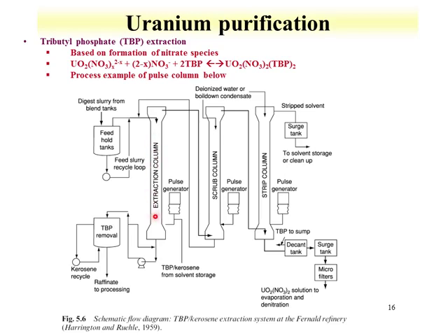As that drop moves down the column, it will form the uranyl nitrate tributyl phosphate species, which then gets extracted into the column. The aqueous phase going here, the organic phase containing the uranium here. The organic phase is taken, added to the scrub column. So this could be the same concentration of acid, so let's say 3.5 molar. As the organic bubbles float up, any metal ions that aren't the uranium can be preferentially removed. The uranium preferentially stays in the organic phase.